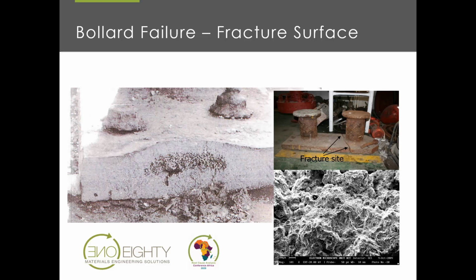What's very significant about this image is that the metallic fracture surface is still shiny. It says no corrosion on that fracture surface, and I'll come back to why that's important later. There was an allegation that this was a fatigue fracture. And if it was a fatigue fracture, in other words, a slow and insidious propagation of a crack over a long period of time, there would be corrosion on the fracture surface.